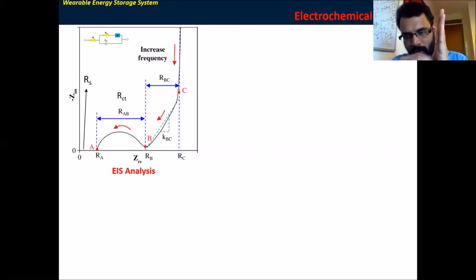Then when your ion is absorbed on the surface of the conductive electrode, this ion diffuses through the surface and the bulk of the material. If it is a conductive material, you can see here there is a semicircle, and this resistance may be very low. It's called the charge transfer resistance. Also, in an electrochemical double layer capacitor, the surface reaction is very important, that is, how the electrochemical double layer is forming. This straight line, toward low frequency at the top of the y-axis, is the area where the electrochemical double layer formation occurs, and that resistance is also very important in the performance of the supercapacitor. This is called impedance spectroscopic analysis.